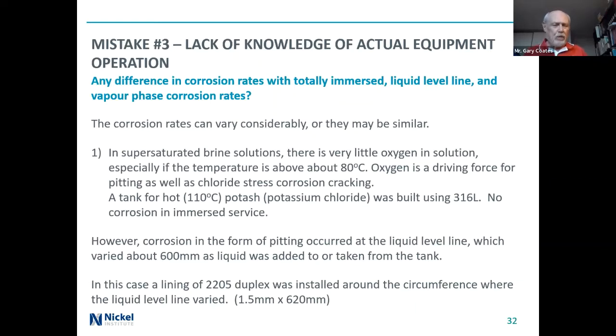Take the oxygen out, even 316L will work fine. So this particular tank stored hot potash at 110 degrees C, and they used 316L because it was fine in the immersed service. But where it was right at the liquid level line, of course, you have higher oxygen content there, and you did get pitting.